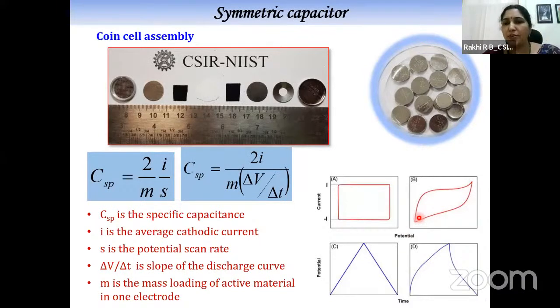And then for galvanostatic charge discharge, if it is a perfect supercapacitor, an ideal EDLC capacitor, we are expected to get a triangular shape, but in the actual case, it will not be perfectly triangular. Then after we make the capacitor cell, we do the electrochemical measurement. Then from the electrochemical measurement, we calculate the specific capacitance.